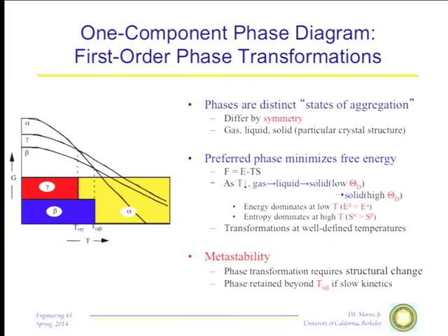Temperature, alpha drops below beta at this temperature, so our phase diagram would be a one-dimensional diagram along this axis, which would show phase beta until this temperature T alpha beta and phase alpha above it. And there may be more phases on this diagram. They would always be the ones that had the lowest value of the free energy.